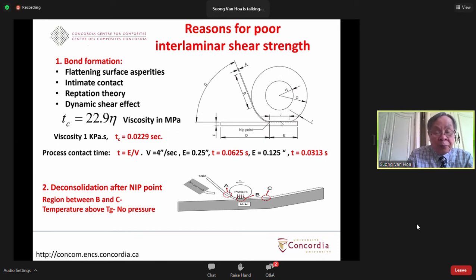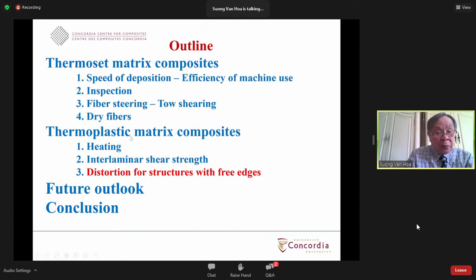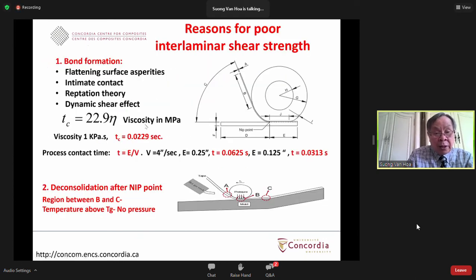Now, there was an estimate of the time required for the reptation to take place across the bond. This gives an equation as a function of the viscosity, where eta is the viscosity in MPa. Now, if the viscosity obtained is around 1 kilopascal second, then the time required for the contact has to be about 22.9 milliseconds for it to happen. On the other side of the picture, if you take a look into the parameters of the process, the time that this is in contact is equal to the contact length divided by the velocity of motion.